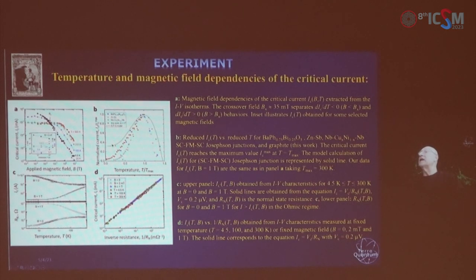Then there is a comparison between the data that we measured on graphite and the usual superconducting data on a usual superconductor, and you can see the immediate similarity between them. And what is beautiful is that basically this curve is described by the model for the superconductor-ferromagnet-superconductor Josephson junction.